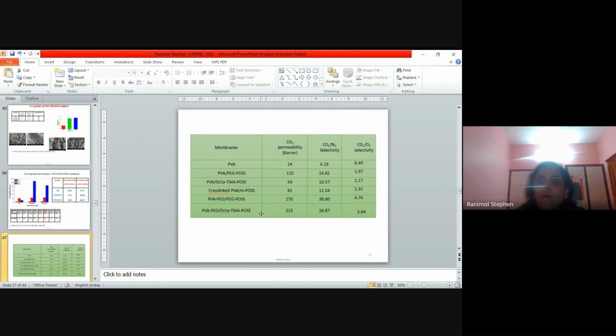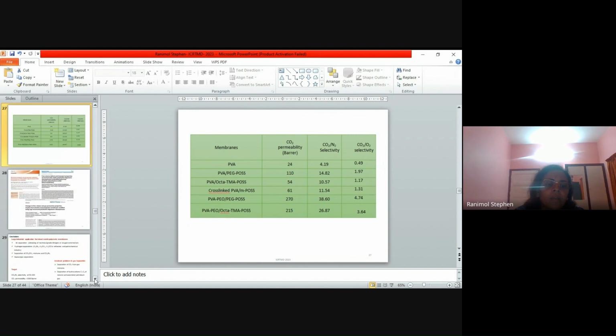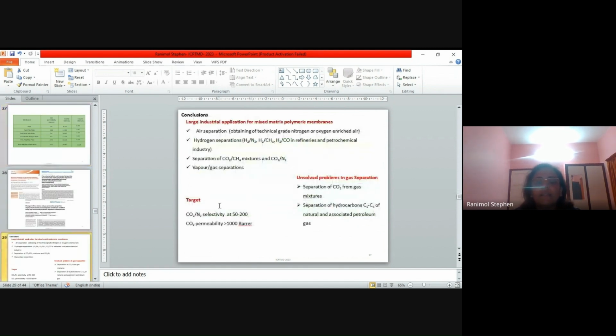So we have obtained a good selectivity for PVA blended with polyethylene oxide because the carbon dioxide affinity is higher, as the ether linkage is there. So carbon dioxide affinity is higher for this system. So the selectivity obtained is 38.60. But the target for gas separation membranes is still open.